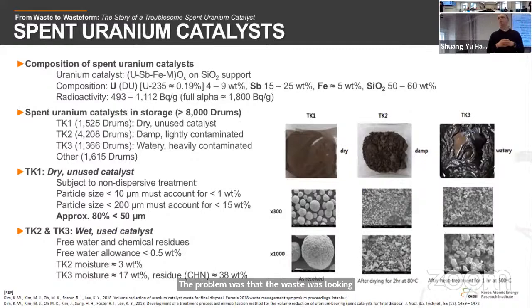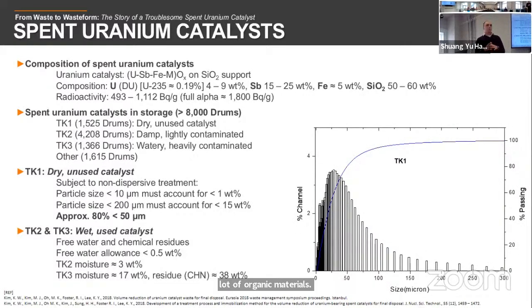So we had the dry catalyst that was unused. We had wet catalyst and used catalyst, which contained a lot of organic materials. Unfortunately, due to disposal regulations, we can't dispose of it directly, so it had to be treated. There were certain constraints for the disposal site at Gyeongju, where you can't have free water or chemical residues. The free water allowance must be less than 0.5 weight%, so we have to ensure that the material is dry. And the particle size also has to be under a certain loading. As it says here, you can't have more than 1 weight% under 10 microns, and not more than 15 weight% under 200 microns.